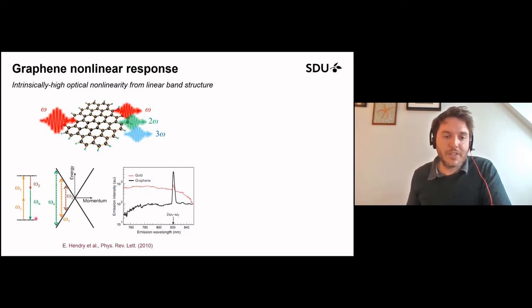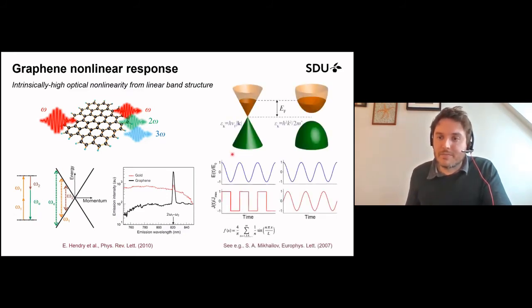So for some process like wave mixing, where we have 3 different frequencies involved, this can already give you a boost. But another appealing property is if you just look at the electron motion within these bands. If an electron is being driven by an electromagnetic field that's oscillating in time, it goes back and forth across this band. And as it does that, effectively its velocity doesn't change magnitude, but it changes its direction instantaneously. So the currents will look like this square wave, going from one direction to the other, dramatically changing. And this is already giving rise to intense harmonic generation of light. And that's in stark contrast to conventional materials described by a parabolic dispersion relation, where you just recover a response at the fundamental frequency.